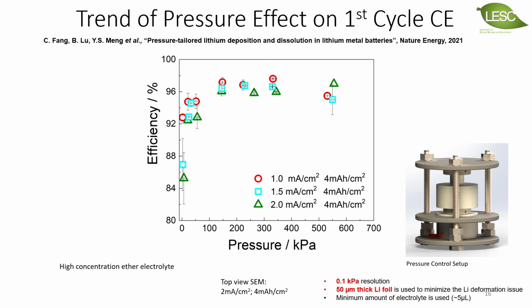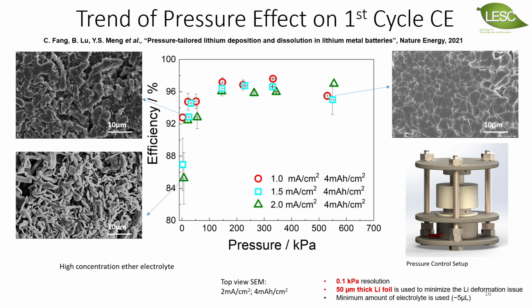So the goal is to set up an experimental tool to look at if you put a gentle stack pressure on the electrodes, does that impact the efficiency? And the result was astonishing, okay? Because at a very low pressure, the electrochemically deposited lithium are extremely porous.